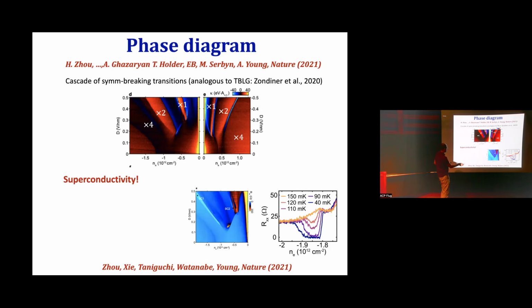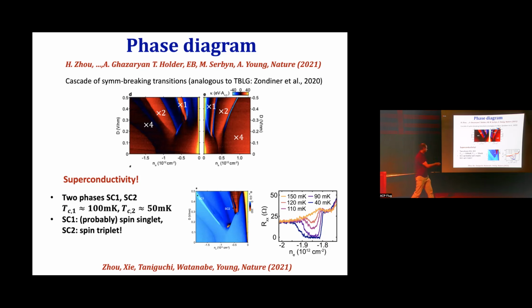The color is different here. The quantity that's measured is different. This is the electrical resistance. It actually goes to 0. These 2 light strips here. Okay. So two distinct superconducting phases called SC1 and SC2. This is just a resistance as a function of density, and you see it going to 0 at low temperature. The TCs are quite low, 0.1 degree Kelvin or even less.